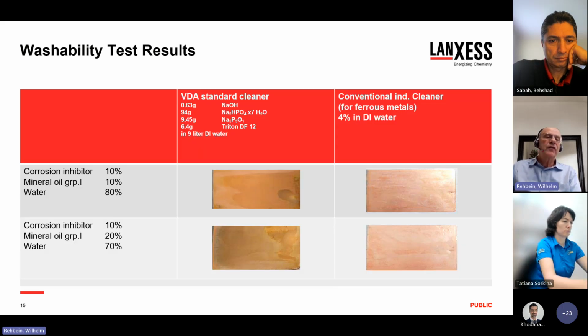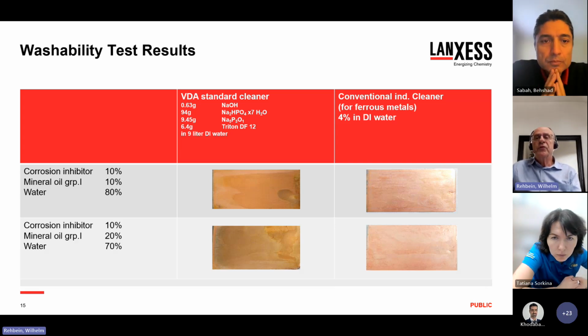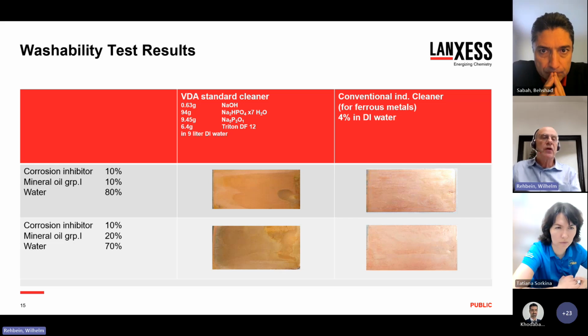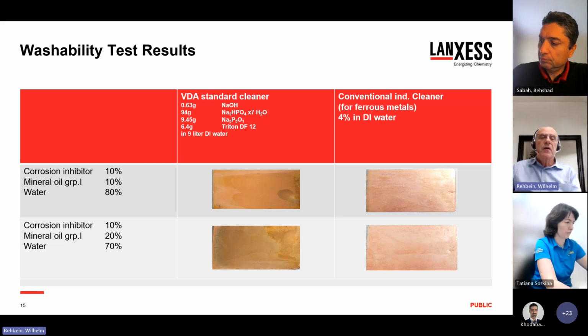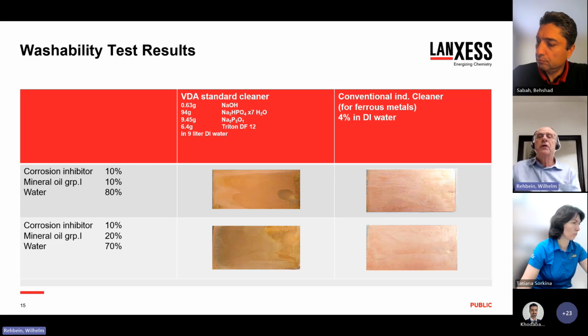And as you can see here on these photos, with both rust preventive formulations containing 10% corrosion inhibitor and 10 respectively 20% of mineral oil and 80 respectively 70% of water, with a VDA standard cleaner as well as with a conventional cleaner for ferrous metals, the results were excellent, and the clean surface area on the steel sheets was 100%.